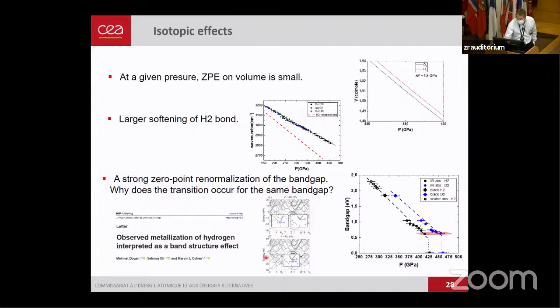But more puzzlingly, you see that the transition of the gap is occurring for the same value of the band gap, which goes in the direction that it's really the effect of the band gap that is driving this transition. And this has been proposed by Dogan and Marvin Cohen this year, that the observed metallization of hydrogen can be interpreted as a band structure effect.